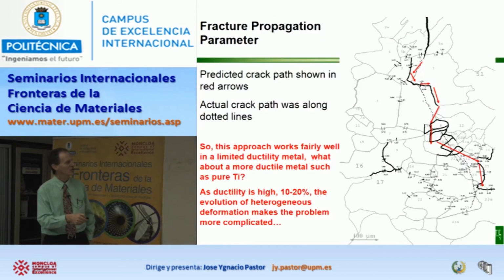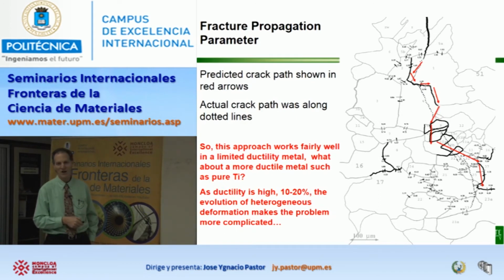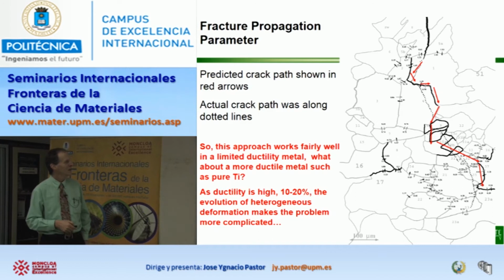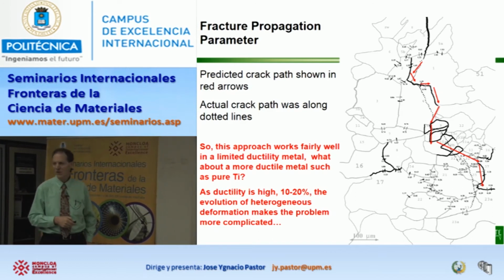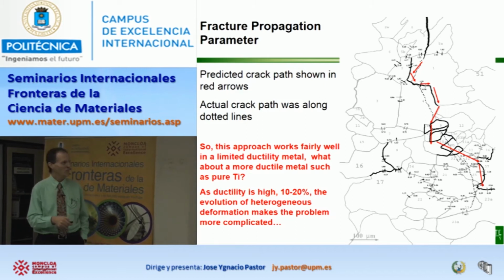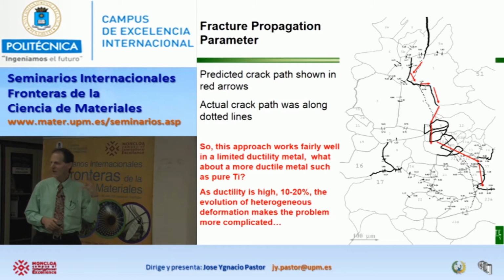So here's the direction of the crack, and it followed basically a path where a lot of these weaker boundaries were. Now, to make a point is that the crack did not really go through the grain boundaries, but it followed a path of weak boundaries. Most of the crack was cleavage, which goes right through the grains instead.